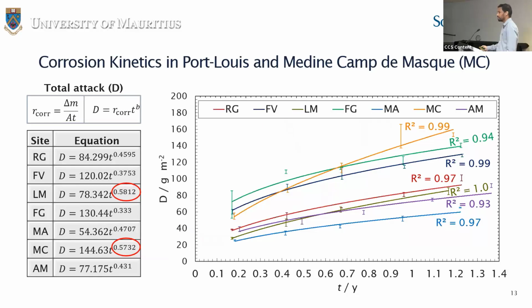Now, corroded metal plates have been removed at specific time intervals for a mass loss analysis to determine the corrosion rate. This corrosion rate has been used to calculate the total attack, capital D, which represents the degree of corrosion, which equals the corrosion rate times time of exposure to the power of B. B is a time exponent whose value depends on the environment and the metal.